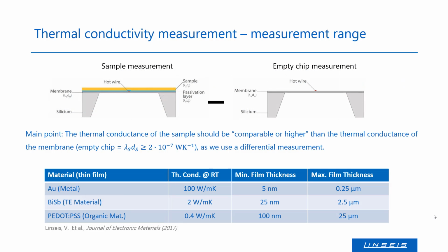For the evaluation of the thermal conductivity of the sample, we use a differential measurement of the coated and uncoated chip. Because of this, the thermal conductance of the empty chip is an important parameter for the sensitivity of the chip, as it defines the measurement range.